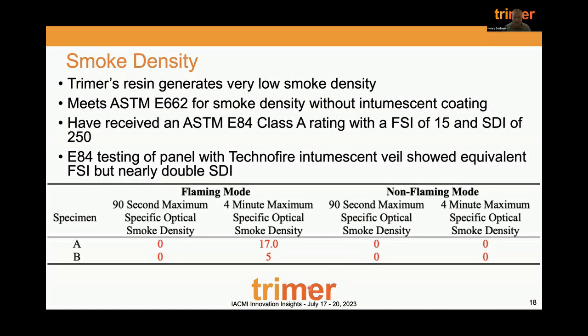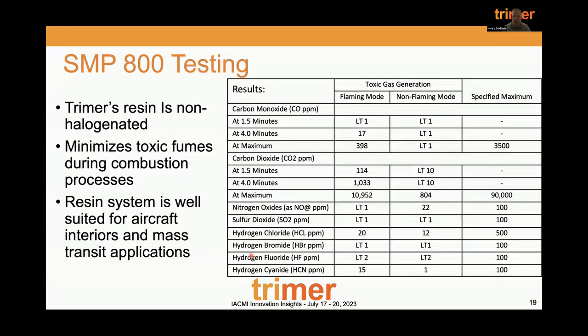We've recently, with IACMI funding through the programs that have been supported from the new consortium, we've demonstrated for Rinco composites that we have a Class A E84 rating with no intumescence. So we can do that with just neat resin itself. Our flame spread is 15 and our smoke index is 250. We actually had lower smoke generation from our neat resin than with an intumescent, and so we can really just use our system and reduce cost that way. SMP 800 is a smoke toxicity test. There's no smoke toxicity issues here. We're an unhalogenated system, and no styrene content, nothing like that. Our VOCs are very low, so we easily meet a smoke toxicity requirement.